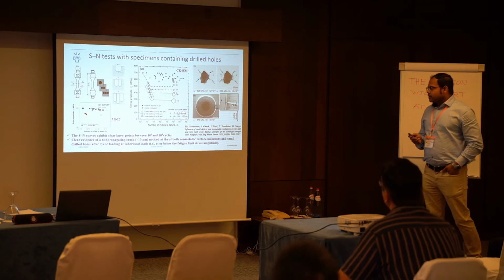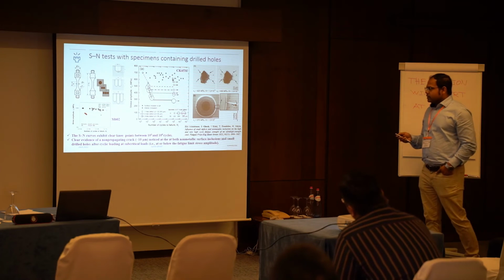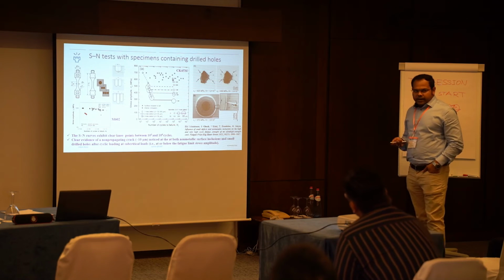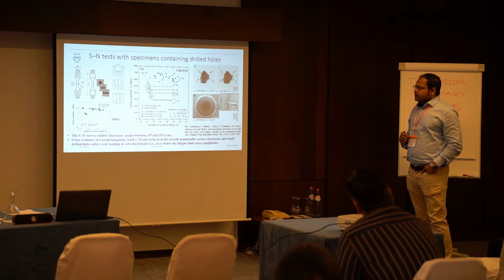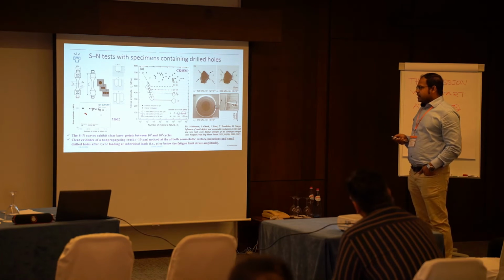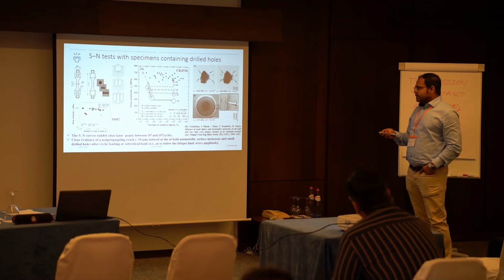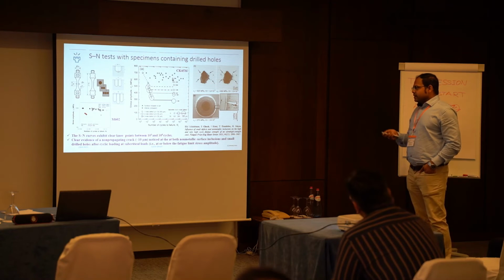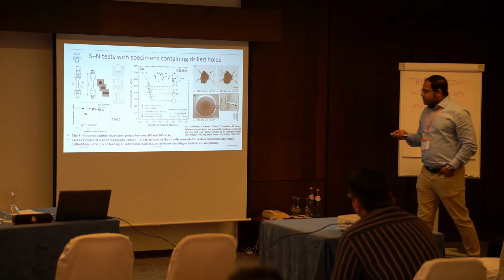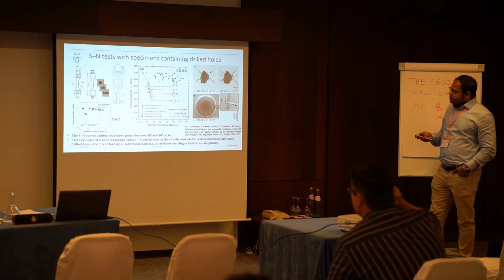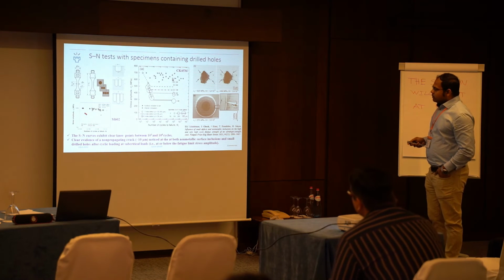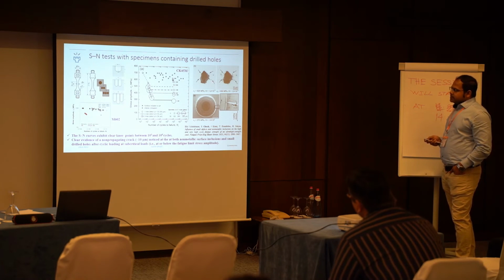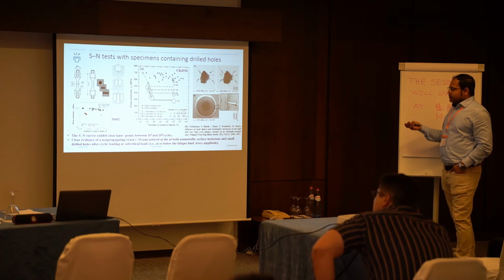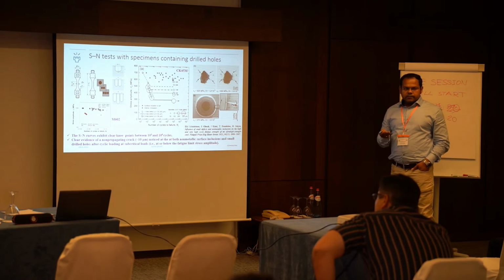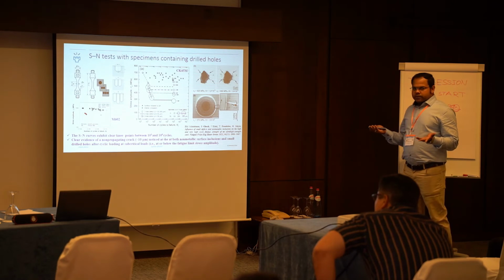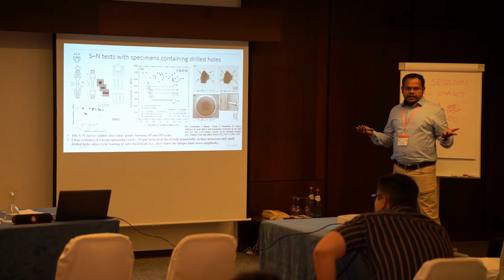Next, for my own interest, I wanted to see how artificial defects affect the fatigue property. We prepared drilled holes of different diameters, and then measured the very high cycle fatigue property under the same conditions. As expected, depending on the size and shape of the artificial defect, the fatigue limit is significantly reduced. One more thing I want to highlight here: it is well known that if there is a crack initiation, it would propagate drastically and there will be failure. As per the definition, the fatigue limit is the threshold limit where there is no crack initiation or crack propagation.